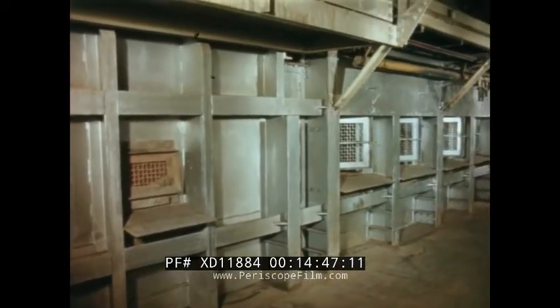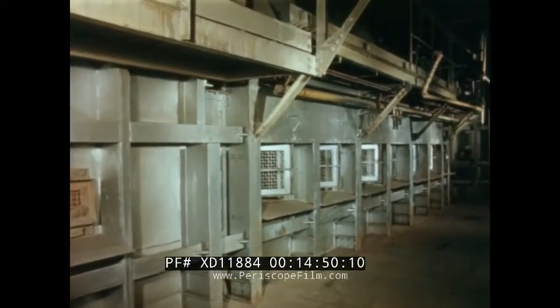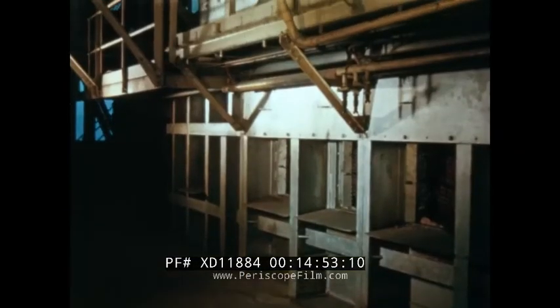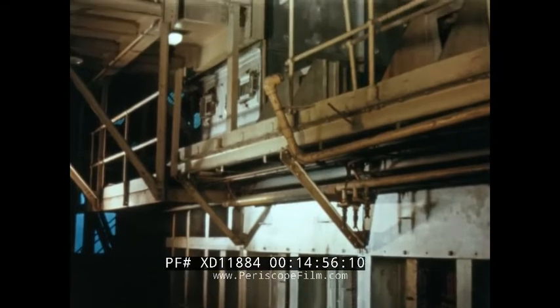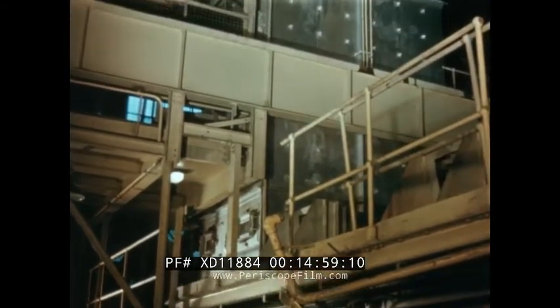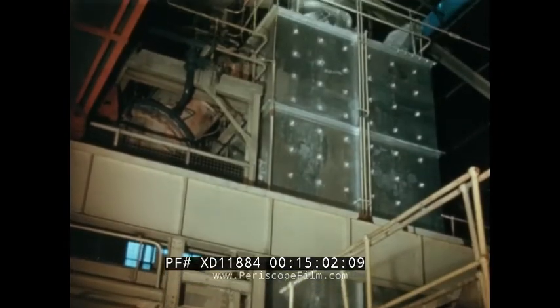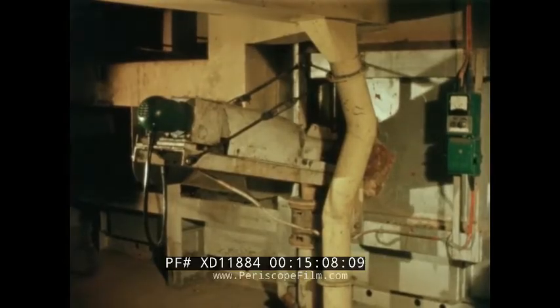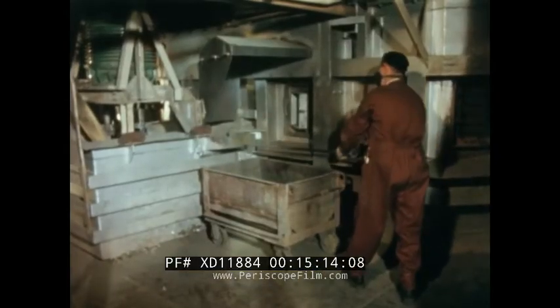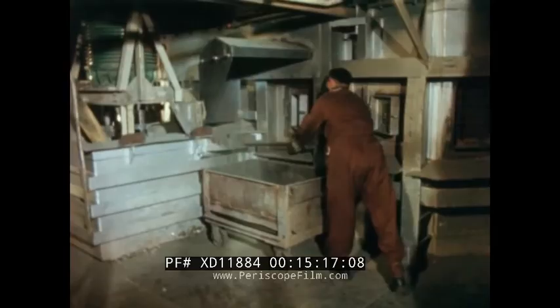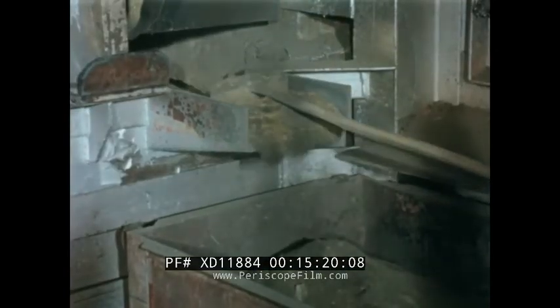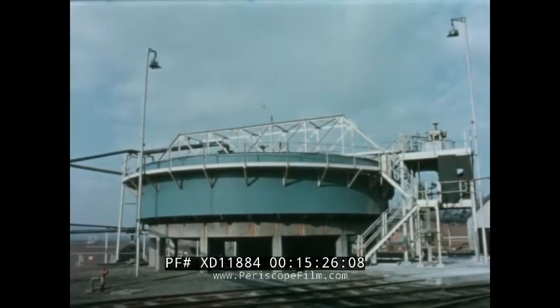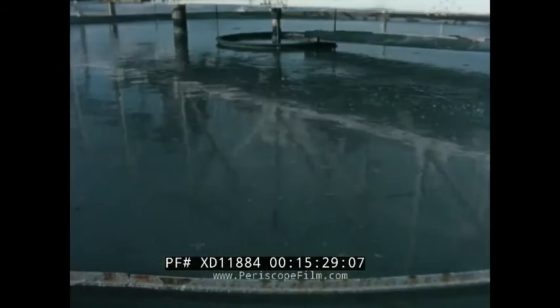Inconspicuous as it may appear from the outside, this lead splash condenser is the very essence of the Imperial smelting process, because it's here liquid zinc is recovered from the blast furnace. Dross, a byproduct of the process containing zinc and lead, is removed from the condenser and then recirculated to the sinter plant. Blue powder from the scrubbing system is recovered in this Dorr thickener and also recirculated to the sinter plant.